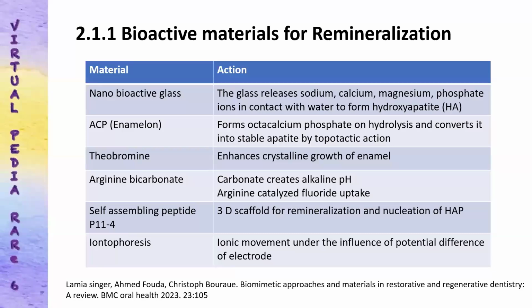Self-assembling peptide, it creates a 3D scaffold which helps us to have nucleation of hydroxyapatite crystal, and it increases the stable formation of hydroxyapatite layer over the demineralized surface of the tooth. Iontophoresis. Iontophoresis is nothing but the movement of calcium and phosphate ions under the influence of the electric current. The potential difference in the electrode drives the movement of the calcium and phosphates, which causes deposition in the demineralized area.